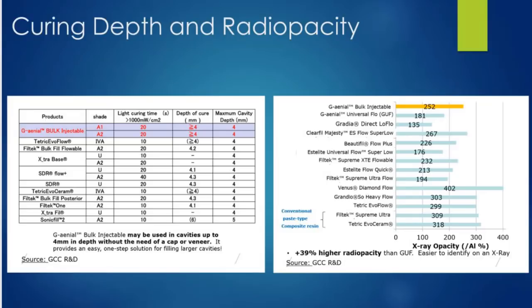We also can compare it to many of the other materials out there for depth of cure and radiopacity. As far as both go, they are certainly in a similar range to everything else that's out there. Again, I am always very leery of the deeper depth of cure materials, especially because the deeper the box gets, the more likely we are not to cure a restoration because of angulation or because of distance away from the cavo-surface margin. So keep that in mind, but typically we're seeing a nice radiopacity as well on the radiographs following.